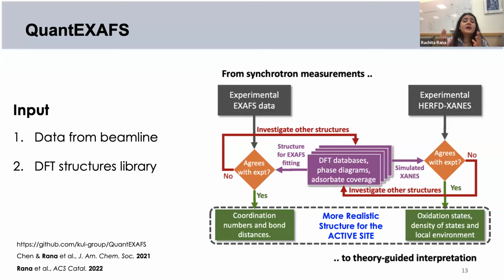So the idea is QuantEXAFS uses xraylarch, FEFF, and xraylib in the backend. When you have experimental EXAFS data and an exhaustive database of these DFT optimized structures, you can generate a model for each of those structures using QuantEXAFS, and then QuantEXAFS does a one-to-one mapping of your experimental EXAFS data with the model from the structure. So you're not really fitting coordination numbers and bond distances in this case. You have a site and you're just trying to put that piece into the puzzle and see if that fits. And that's how QuantEXAFS works in the backend.